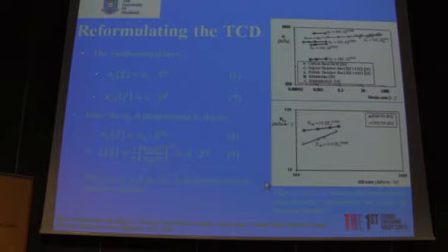From Taylor's book, he mentioned that the dynamic yield stress is proportional to sigma UTS. The reason is that the dynamic yield stress can follow a simple power law. In the same way, we can assume the material inherent strength follows the same power law, as in equation 8. We can then simply apply the same power law to the critical distance L, as equation 9 shows here.